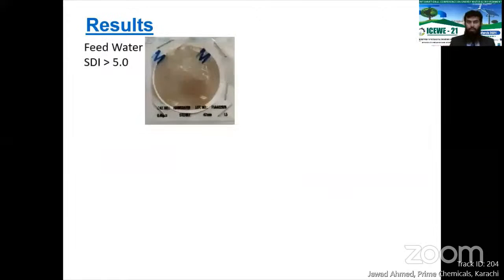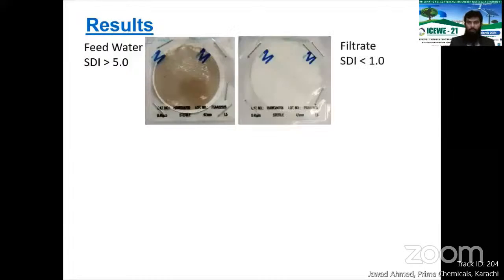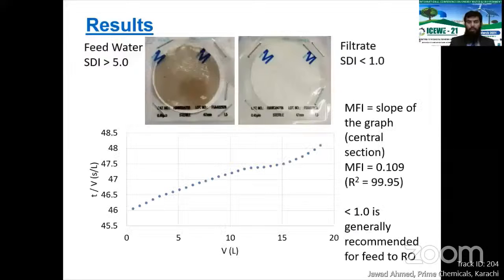Another parameter that we analyzed was the silt density index, or SDI, again a measure of the particles present in the water and their propensity to cause fouling on the downstream RO membrane. On the left, we can see the feed water with an SDI of over 5, and the visible presence of colloids and particulates on the SDI filter paper. For the filtrate, there is almost no deposition, with an SDI value of less than 1. We also calculated the modified fouling index, or MFI value, which represents the slope of the curve here.